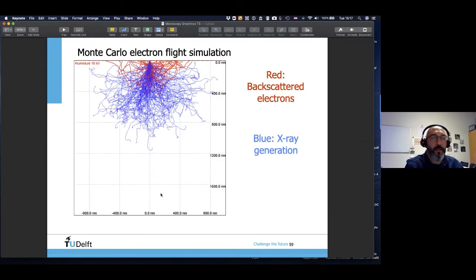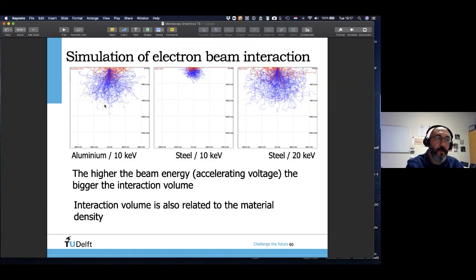Okay, which is an example here. You see, if you model based on, we assumed that it was aluminum and 10 kilovolts accelerating voltage, it would generate electron trajectories like this and X-ray generation from here. So if your phase is so small right here, and you're interested in analyzing the chemical composition of this, forget about it at these settings, because you're getting information from the neighboring phases, you see? So important. And these are for different materials and for different accelerating voltages. You see, you can change the interaction volume.